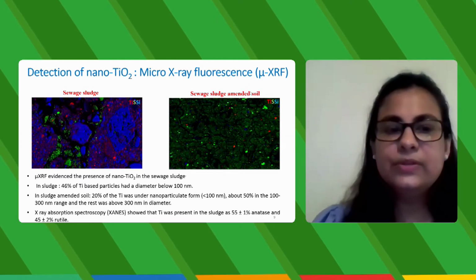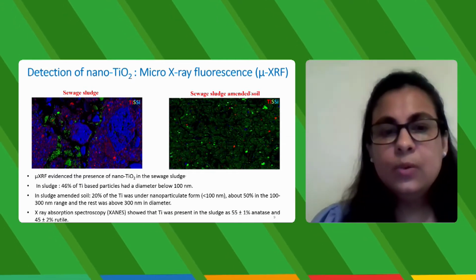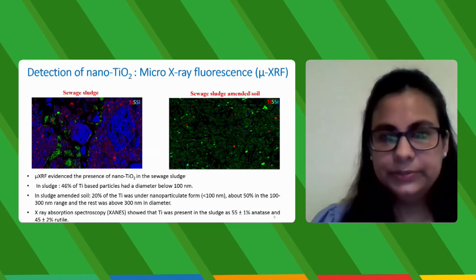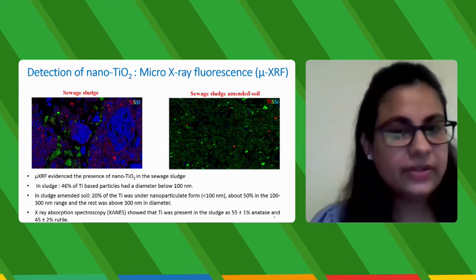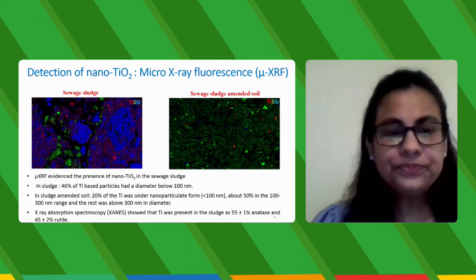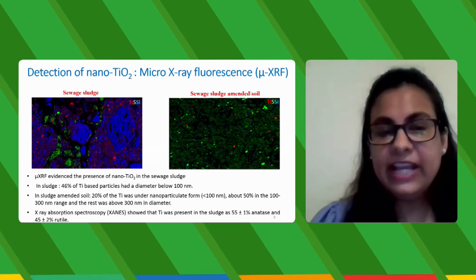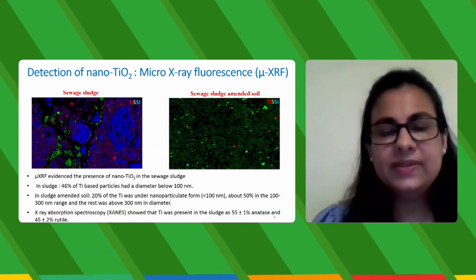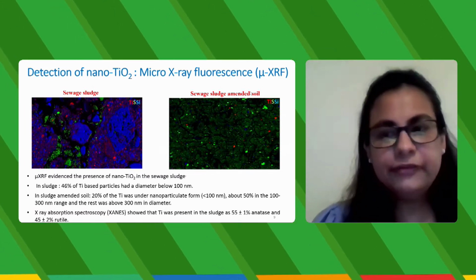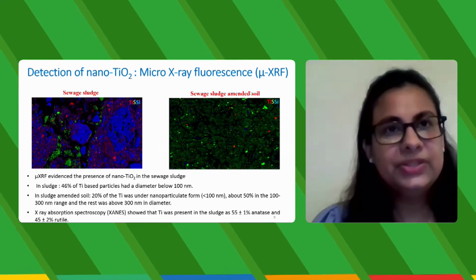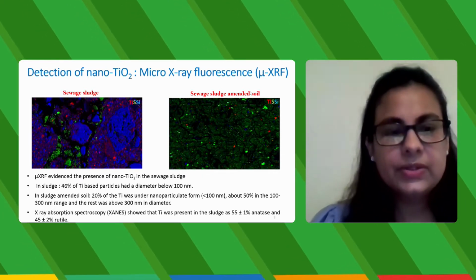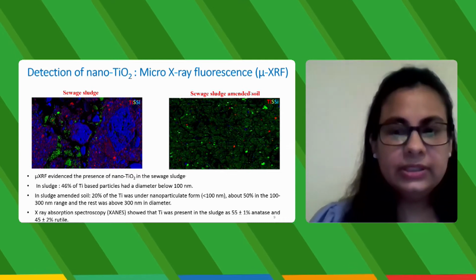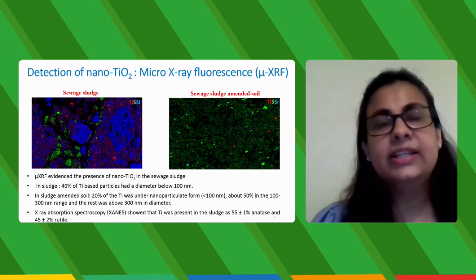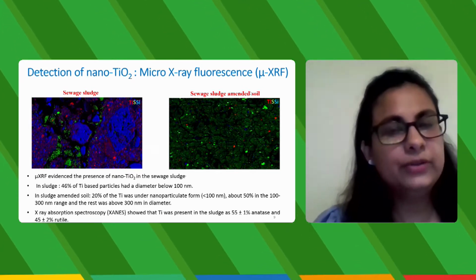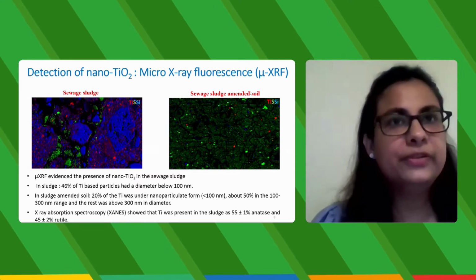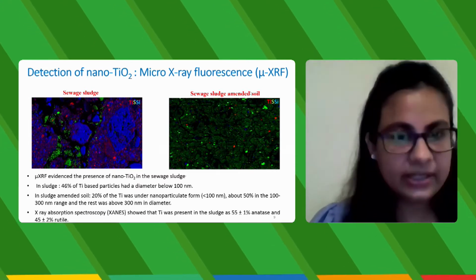We found that in the sludge, 46% of titanium was below 100 nm in diameter, which fits the definition and range of nanoparticles. In the soil that we amended with the sludge, we found 20% titanium under 100 nanometers, 50% between 100 and 300 nanometers, and the rest above 300 nanometers. And we also found that 55% of the titanium was anatase and 45% was rutile. Anatase and rutile are two forms of titanium, anatase being more reactive than rutile.